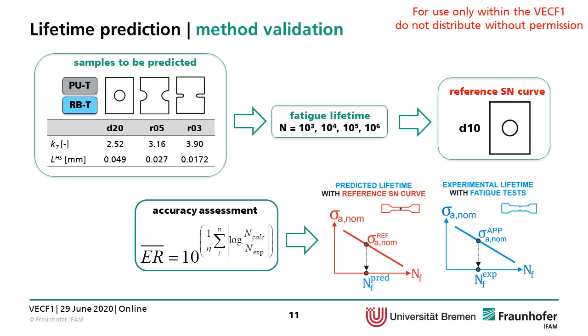In this case, we use as accuracy assessment the error factor, which is basically the factor of your accuracy. For instance, if you have an experimental lifetime of 10,000 and your prediction was 20,000, then your error factor would be 2. Or if you have an experimental lifetime of 200,000 and then you predict 600,000, your error factor is 3. And comparing the predicted lifetimes and the experimental lifetime.